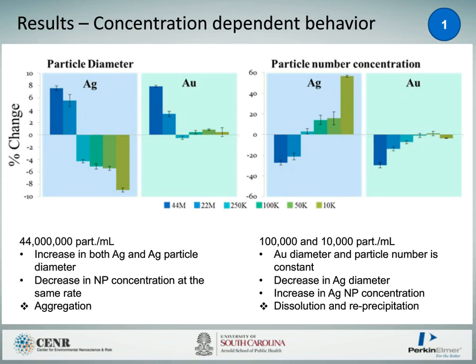So looking at the full set of results, we've got a percentage change. If you have a positive percentage change, we're getting a larger particle diameter. With a negative percentage change, we're getting a smaller particle diameter compared to the original. And the same with the particle number. If you're getting a negative change, we're getting fewer particles, and if we're getting a positive change, we're getting more particles. So I'd just like to reiterate the point that at the higher concentrations, we're getting what looks like aggregation, and when you go to lower concentrations, we're getting this dissolution and reprecipitation, which is something that we haven't really observed very easily before.